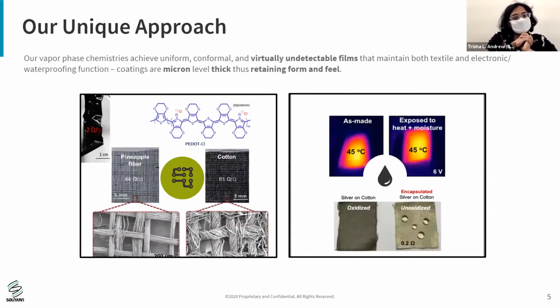Next slide, please. The advantage of using chemical vapor deposition is that if you zoom down into the nano and micro scale, you actually get a completely conformal film. These are scanning electron microscope images of pineapple fiber fabric and cotton. You can see the yarn structure, the very disordered yarn structure on the left. These are actually SEMs of the coating on that yarn structure. You cannot actually distinguish the coating from the structure of the fabric, and that's because you get this entirely conformal coat of the functional polymer, no matter what kind of structure you're using, directly on the fabric itself. And the same applies again to our protective coatings.